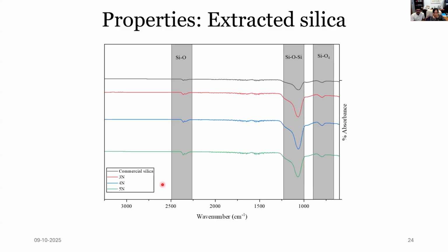So coming to the silica extraction process results, we wanted to know whether the silica that we extracted is comparable to the commercial silica that we have. In this figure, we can see the FTIR image, where the bond between silicon and oxygen is clearly seen between the range of 2250 to 2500. And the SiO-Si asymmetric stretching, which is enhanced between 1000 to 1250.